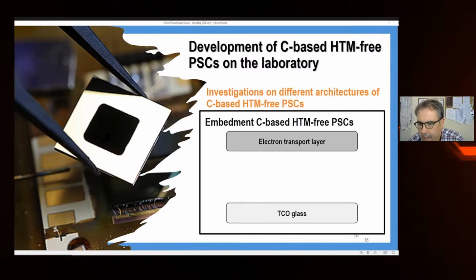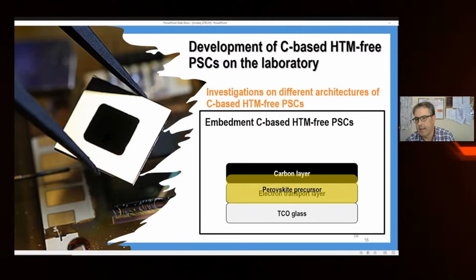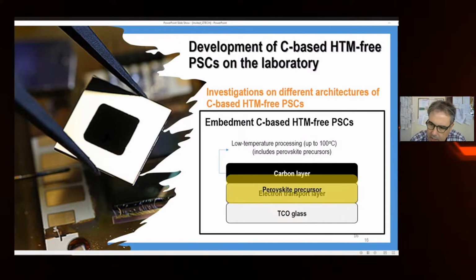The next one is the embedment, as it's called, a carbon-based HTM-free perovskite solar cell. We directly put the perovskite on top of a mesoporous layer, and then the carbon. Finally, this is more attractive because the carbon process is now up to 100 degrees. So we have to think that we make an energy saving at the preparation stage. And finally, it is something which sounds attractive.